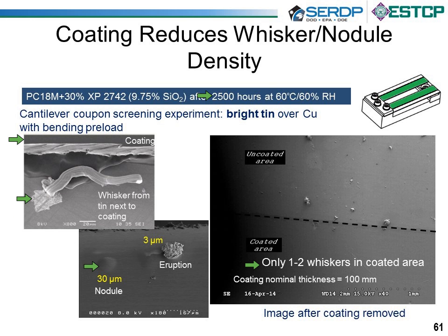Where the coating was like 3 microns thick, we had an eruption that broke through. Where it was a little thicker, we had 30 microns, we saw the nodule grow underneath the coating, but it did not yet penetrate. So I think that's very encouraging. We're seeing an actual inhibition of whisker growth by this particular coating, which is our PC18M with the nanosilica.